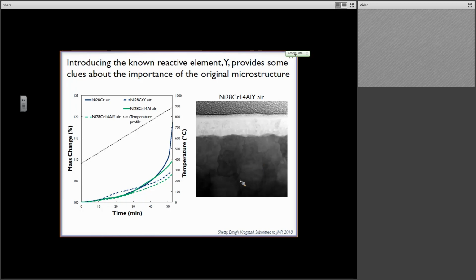And the really dark gray down here, that's the original alloy film. If you could see the contrast a little better, and maybe those of you on the webinar actually can see the contrast better, the grains are equiaxed, so we don't have the columnar structure anymore. And this lighter region up here, that is the oxide scale. It's very dense, it's nice and continuous. And I'm going to overlay some EDS maps on top of this to give you a feel for what's happening during this process. The first one I'm going to overlay is the yttrium EDS map.